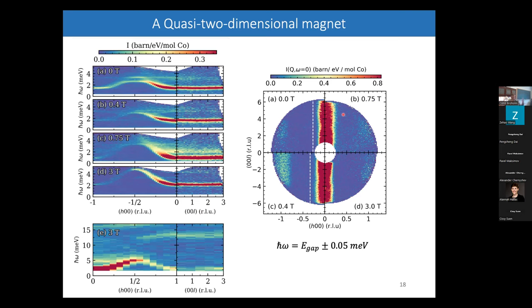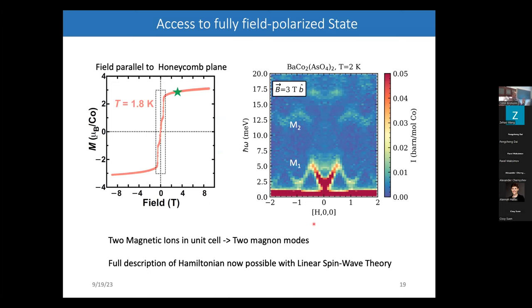Actually, we've zoomed in on that a little bit more by looking at a couple of different fields, 0, 0.4, 0.75, and 3 Tesla. At each field, we've shown the intensity as a function of in-plane and out-of-plane wave vector right near the gap energy. We know there is an interaction between planes, but if it was significant in terms of the excitations, then this line would wander, but it actually stays completely fixed. So at all of these fields, we don't detect significant interlayer dispersion. It's really a completely flat mode. So we very much go to a two-dimensional model.